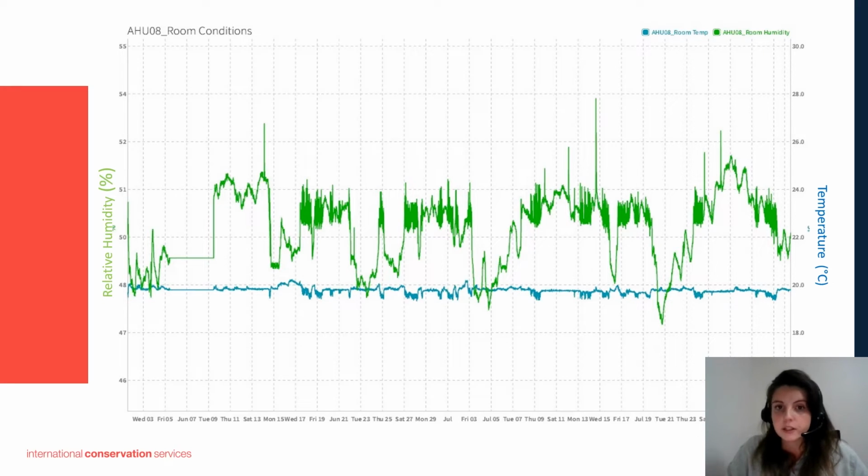Reducing the fluctuation of temperature and relative humidity as much as possible reduces the possible migration of the surfactant to the surface. However, the irregular pattern on one of the panels suggests that its proximity to the environmental controls from the roof could be affecting this section more. The irregular pattern could also be due to the paint application method. This area could have a different thickness of paint and/or primer, meaning that the panels have a different percentage of surfactant content and are reacting differently.